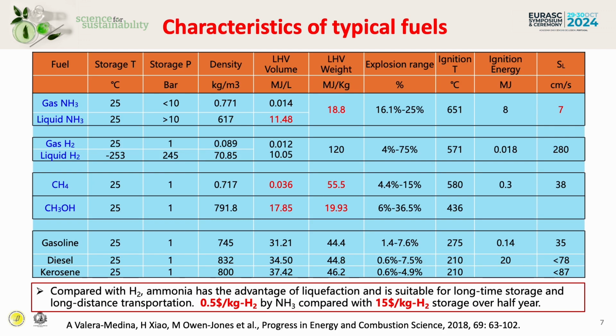This table shows the characteristics of typical fuels. You can see the gas-phase fuels like ammonia, hydrogen and methane usually have a very low energy density per volume. But ammonia can be easily liquefied at room temperature and 10 bar. So liquid ammonia can have 11.48 megajoules per liter. The energy density is already 1/3 of typical liquid fuels like gasoline and diesel. That is very attractive. Compared with liquefied hydrogen, it's more economic.